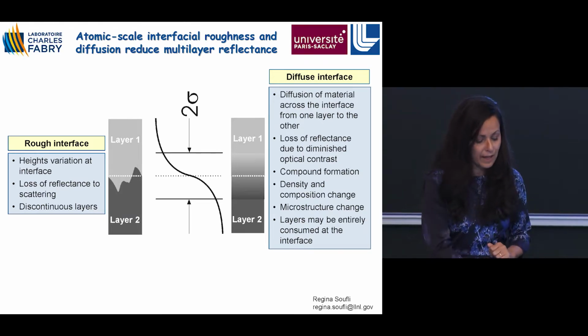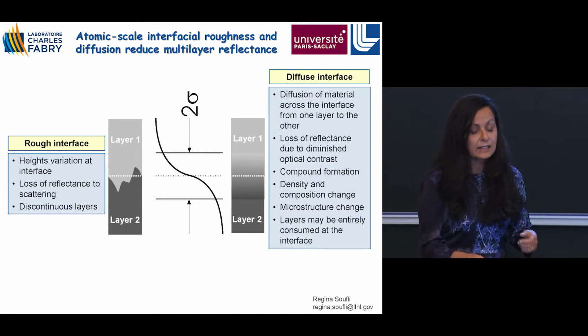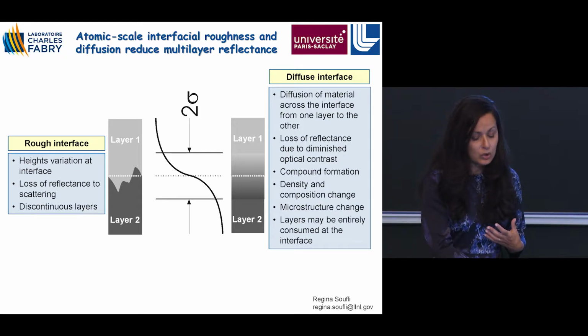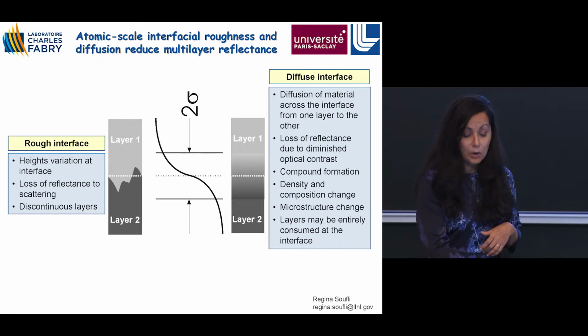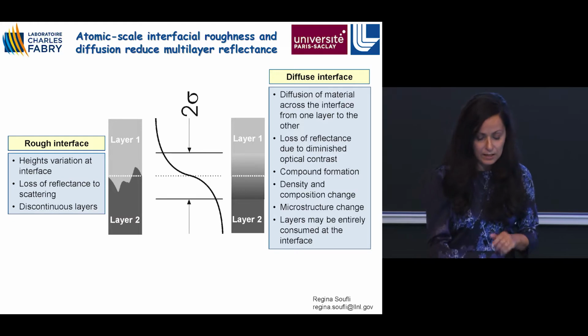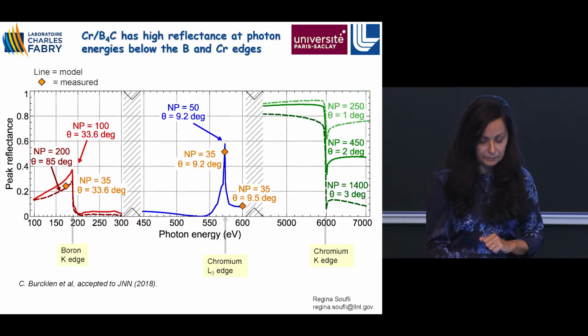You don't want to have that. In extreme cases, you may even have discontinuous layers in the multilayer. And the other effect is diffuse interface, meaning diffusion of one material into the other. There you lose reflectivity due to diminished optical contrast between the two layers. You may have compound formation at the interfaces. You may have density and compositional changes, microstructure changes, and you may even have an entire layer be lost inside the interface. And we're going to see that in a minute.